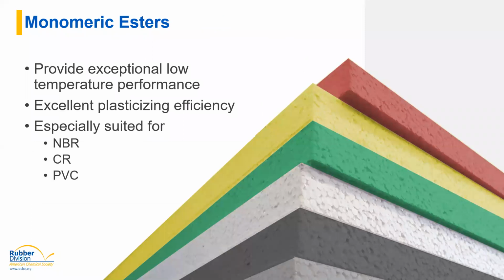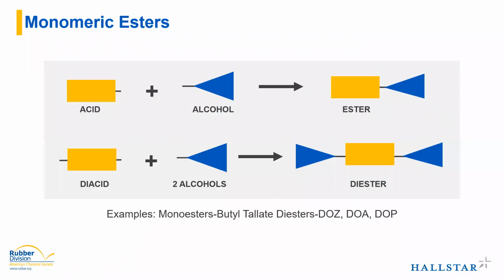So why would you choose one over the other? We'll talk about monomeric esters first. Monomeric esters provide excellent low temperature performance because they are such small molecules. They can move very freely and they can offer excellent flexibility. For the same reason, they have excellent plasticizing efficiency. You usually don't need to use them at very high loading levels to really see an effect and to see benefits. They're really well suited for more commodity elastomers, things like NBR, chloroprenes, and then even PVC blends with elastomers as well. Monomeric esters do very well there.